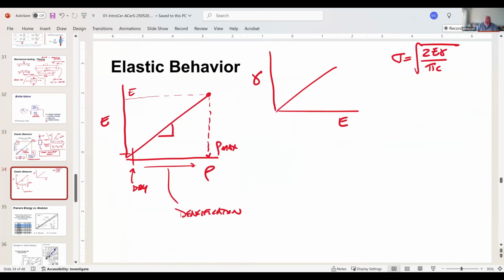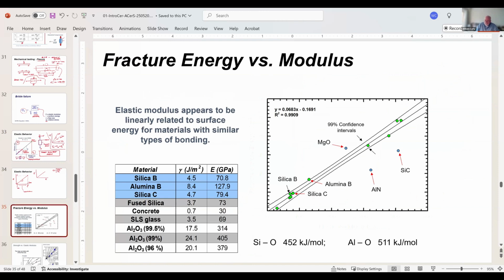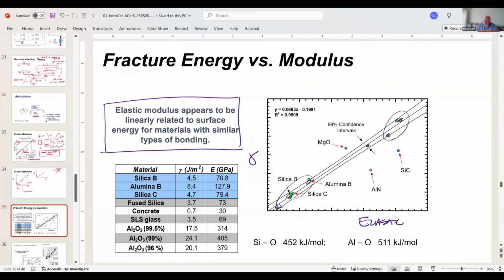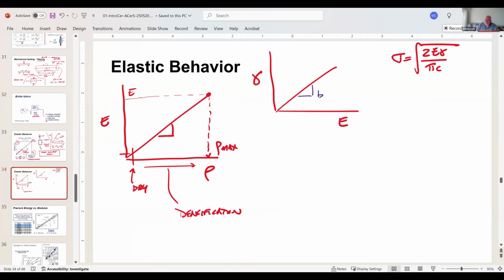Now, this data here, we measured a bunch of different samples, and we found that the elastic modulus appears to linearly track with the bonding. This is elastic modulus, and this is fracture surface energy, and we have a linear relationship of those two for all of these samples, which are all silicate bonded alumina in some fashion. This is alumina up here, this is silica down here, and they turn out to be on the same path. So that's led us to the conclusion that my fracture surface energy change scales linearly with elastic modulus. So I get a slope here, which we call B.